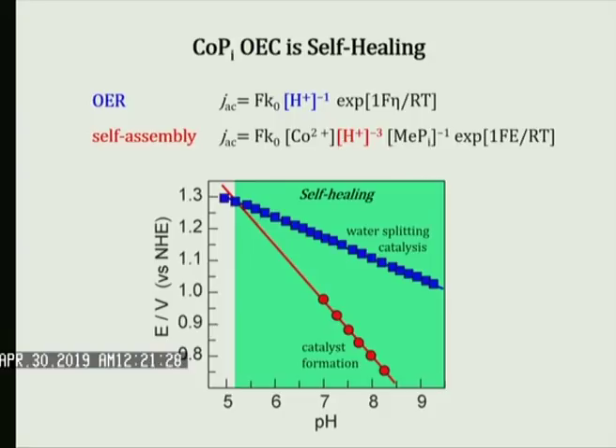So in the blue line, that's the line for how you make oxygen. And the red line is how you self-assemble the catalyst from solution. So let's look at pH 7. We'll look at pH of seawater, anywhere between, say, 6.5 to 7.5, but this entire green region, this is true. So let's just look at 7.